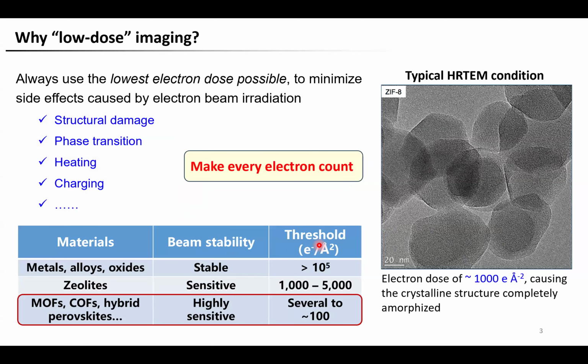In the TEM community, there is a very popular saying, make every electron count, which actually highlights the importance of low-dose techniques, because the electron beam can bring a lot of side effects into the specimen during imaging, including structure damage, phase transition, heating, charging, etc. So to minimize these side effects, we should always use the lowest electron dose possible. Right? So in fact, many materials are conventionally considered unsuitable for TEM study because of their high sensitivity to electron beam irradiation. So once exposed to the electron beam, their structure will be immediately damaged.